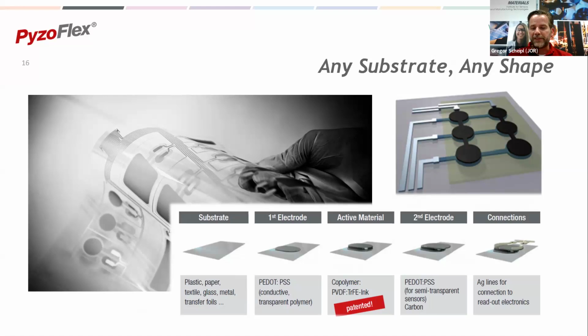So it's the PEDOT:PSS, it's the bottom electrode. Then in the second step, we print the active material. So it's the PVDF-TrFE ink from Arkema Piezotech. The third step is, again, the top electrode. It's like a capacitor structure. And finally, the silver lines in order to connect the sensor to readout electronics. And if needed, we can print a protection layer on top of it.